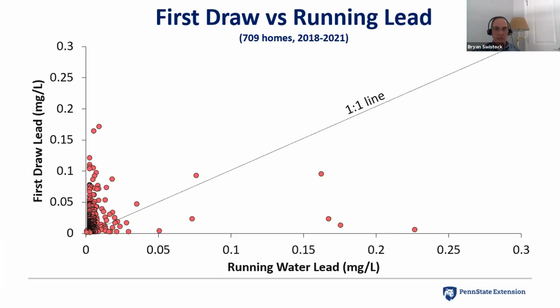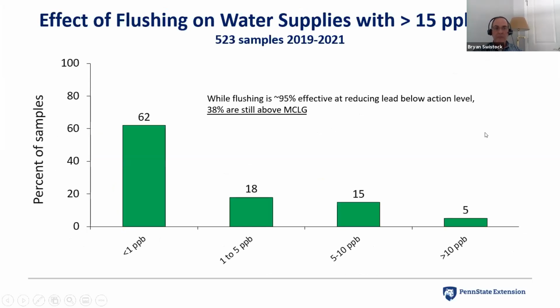We do see these occasional cases out here where lead goes up after running, and those are on a case-by-case basis. We have to go in and try to work with those homeowners and figure out, why is that occurring? Is it just that we didn't flush correctly? Were we getting some sediment out of the pressure tank that had some lead particulate in it? What was it that caused that increase? Thankfully, that's fairly rare though. For the most part, running the water drastically reduces that lead down, again, in 95% or more of the cases.